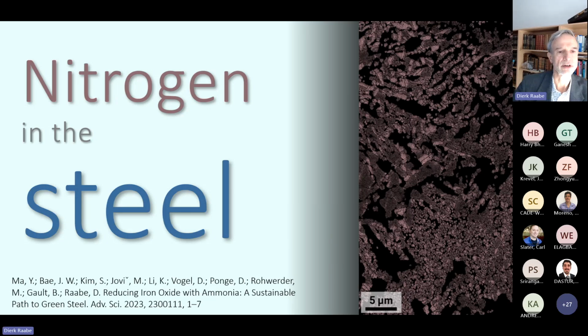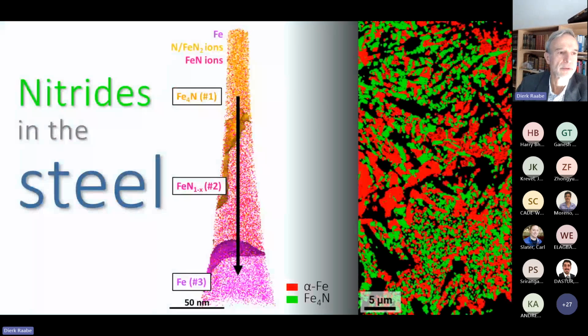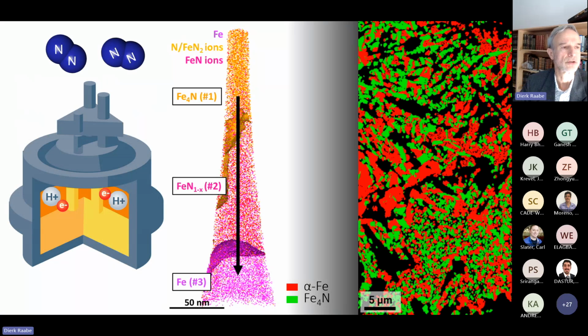So you have pure hydrogen and nitrogen at these temperatures. But indeed, when you go to the atom probe analysis and do phase-sensitive EBSD analysis, as you can see on the right-hand side, you form up to 35, 40, 42% of nitrides. So a very high nitride fraction. Now, this was first, of course, a disappointment. But on the other hand, when you charge these nitrides into an electric arc furnace, due to the high vapor pressure of the nitrogen, the nitrogen is evaporated and you get pure iron, which you again can charge into subsequent metallurgy. So it's in principle all good and fine.